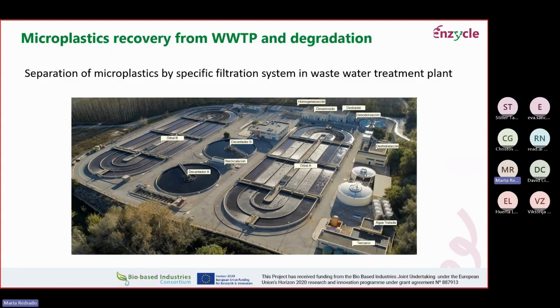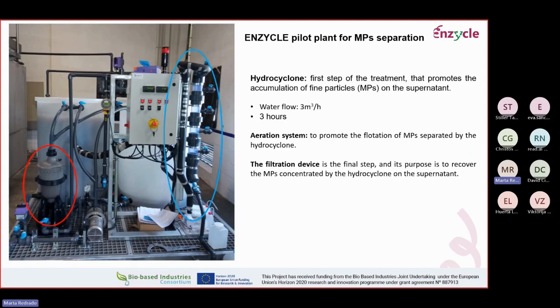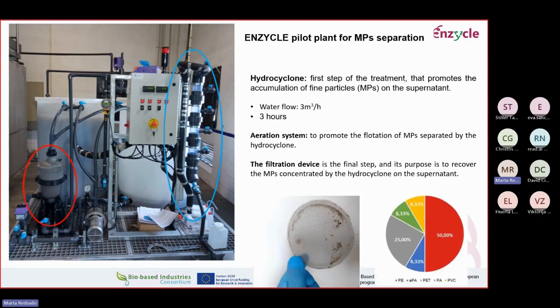And last but not least, as I mentioned at the beginning of the presentation, we were also trying to tackle the issue of the presence of microplastics in wastewater. We have a company, DAM, contributing within Enzycle with their wastewater treatment plant. They developed a system to recover the microplastics from their wastewater plant, composed of a hydrocyclone to concentrate the microplastics, an aeration system to separate the microplastics by flotation, and also a filtration device, which you see surrounded in blue, with meshes of different pore sizes, so we could separate the microplastics by different sizes. So this allowed them to recover the microplastic fractions present in the wastewater in their facility.